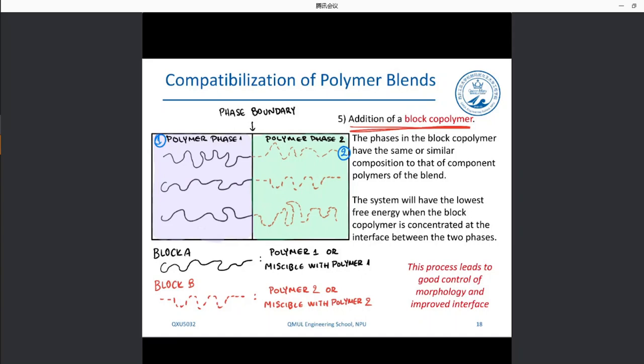How do we make them more friendly towards each other? By adding a block copolymer. This block copolymer has to have blocks that are similar in composition to the component polymers of the blend. So if we have this block copolymer where block A is a friend with polymer 1, thermodynamically friend, I mean they are from the same family of materials, so they keep the Gibbs free energy at a minimum. So we have a block that is from the same family as polymer 1, or miscible with polymer 1. And we have the second block of the copolymer.